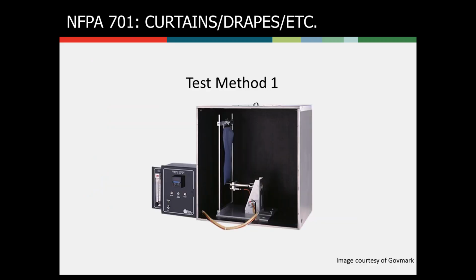And so what I'd like to do is just go through some of the key ones that we discussed and give you a short description of what they are and an idea of what we're looking at. So NFPA 701 applies to a lot of industrial fabrics and textiles that are used. And so there's two test methods within this standard. The first test method is a small-scale test. It's meant for textiles with weights less than 21 ounces per square yard.